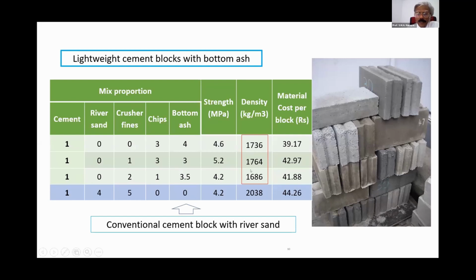So now this table shows the lightweight cement blocks made with bottom ash, 100% replacement. You can see that the weight of the cement block is less than the weight of the cement block with river sand. The price is not much different, right? So you can replace river sand with the bottom ash 100%.